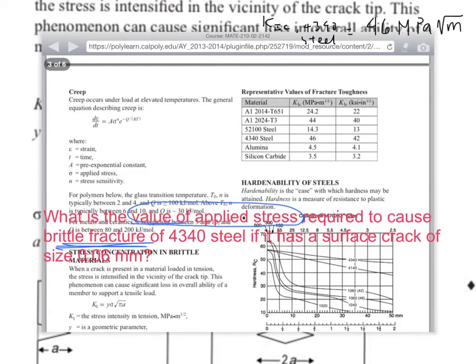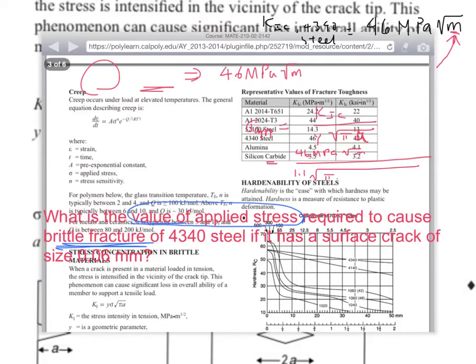Okay, we've got this equation. We've got 46 megapascals square root meters for the K1c value. And I can rearrange this equation so that I'm solving for sigma applied. Sigma applied equals K1c divided by Y square root pi times A. I just need to make sure that I have my A in meters so that I can cancel with this value here. So I'm going to plug these values in. I've got 46 megapascals square root of meters divided by 1.1 for Y, because we're using the exterior crack here, times the square root of pi times 0.06 times 10 to the minus 3 meters.